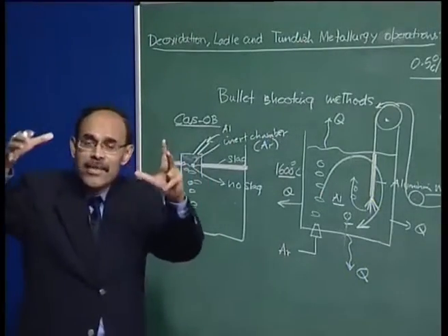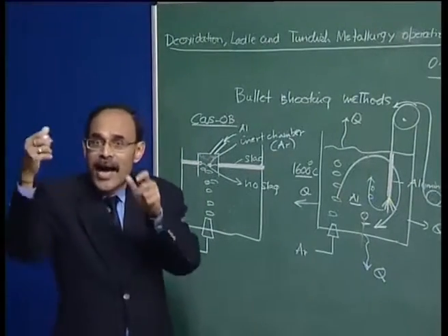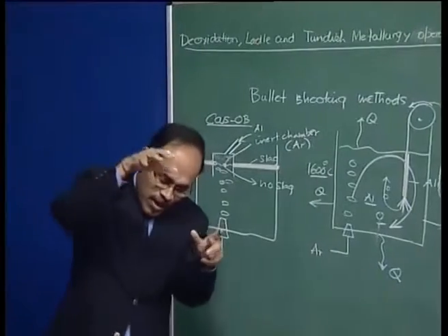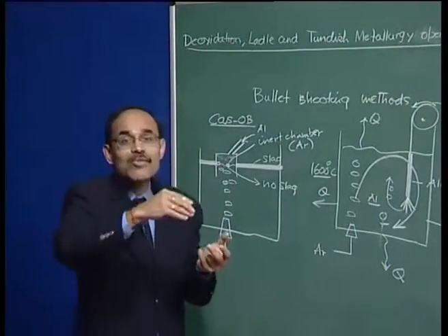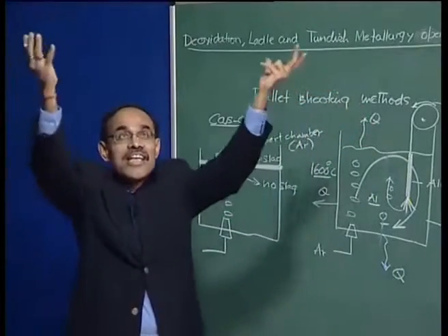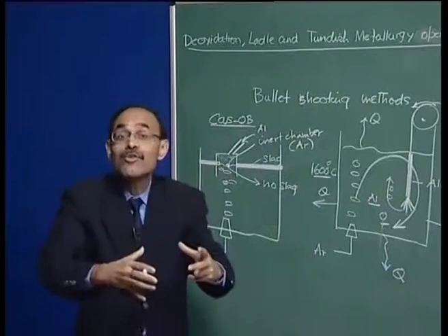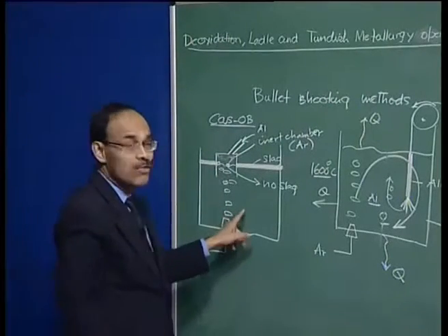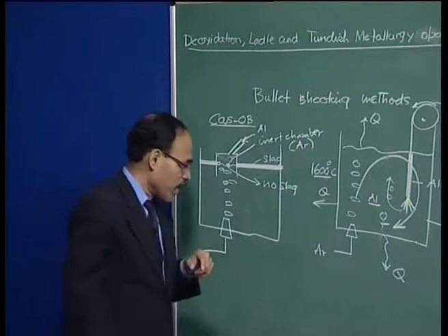So, in the furnace we are using a basic oxygen furnace, we are using oxygen. Now, when you are tilting the furnace and filling up the ladle, during that process the falling molten steel stream draws a lot of surrounding air which contains a lot of nitrogen, as a result of which the material contained in the ladle will contain a lot of nitrogen.